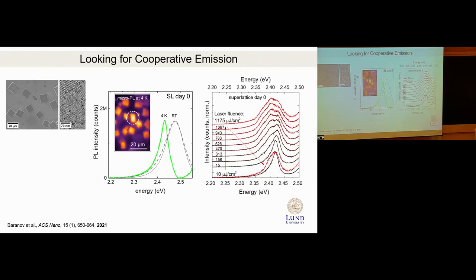The only thing we saw is that when we increase excitation intensity, the photoluminescence broadens and shifts a little bit, but then when you return back, you see that the superlattice essentially has been fried. So we couldn't find any signatures of cooperativity from these simple measurements.